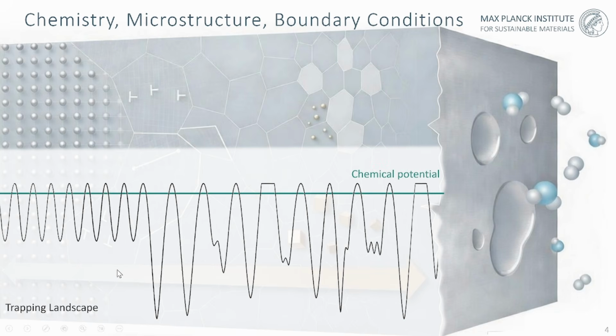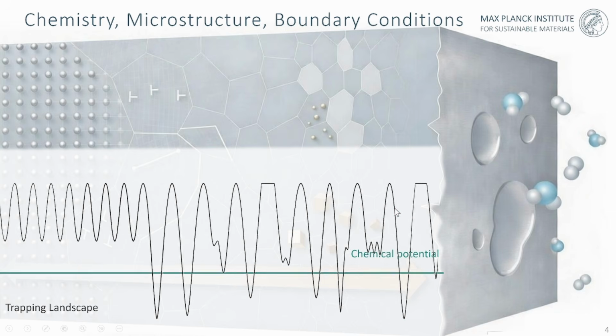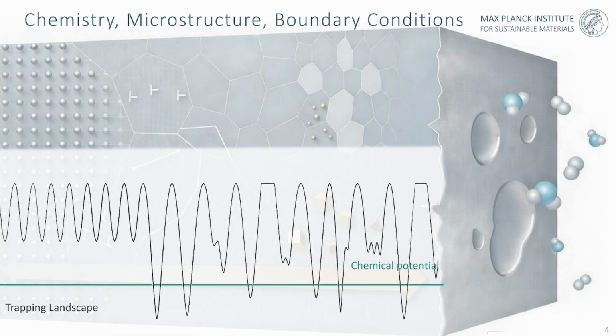And when you now compare that with the corresponding chemical potential level that is given when hydrogen is present, then it depends which of these traps are being filled and which are not being filled when we, for instance, have different scenarios where the chemical potential has a different value. That means aspects such as the temporal effects of hydrogen loading, whether it's a flash exposure like during a welding process, for instance, or whether it's a permanent exposure like in pipeline problems, make this hydrogen embrittlement effect very, very different. So this must be taken into consideration.